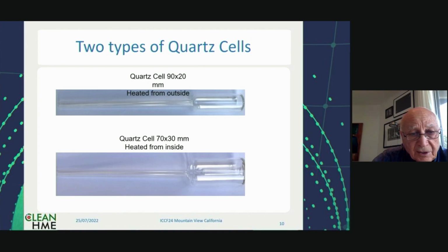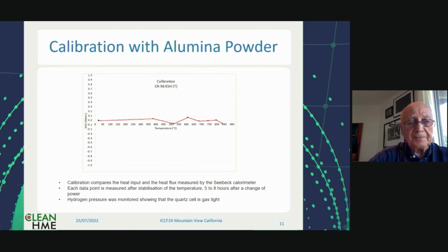quartz cell and another one, a 3 centimeter quartz cell. Next slide. Okay, we have done a calibration because it's important to have good calibration. The calibration is made with alumina powder and hydrogen, and you see that the precision of the calorimeter is pretty good, better than 100 milliwatts up to high temperatures. So this gives us trust in the measurements.